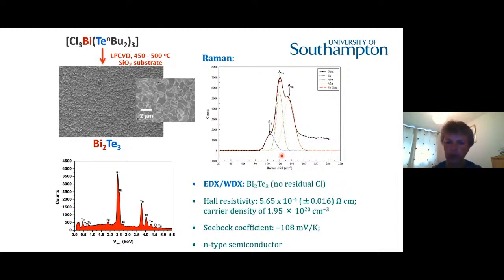for Bi2Te3. Importantly, we can establish from a range of techniques, including energy dispersive X-ray analysis, that we have no chloride incorporation. So all of the chloride that was in the precursor molecule has been eliminated in the deposition process. And we have what appears to be very nice quality N-type semiconductor material of Bi2Te3. So that was a very encouraging situation.